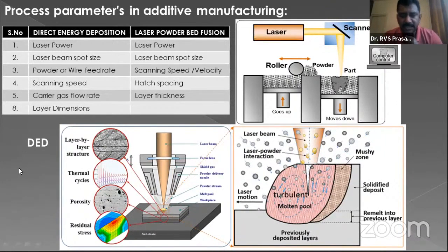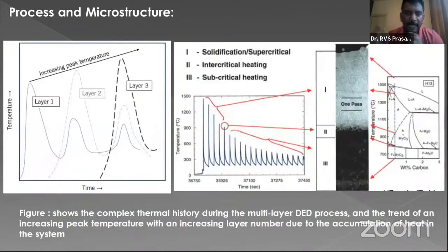However, in the current scenario, by applying these new technologies, one can easily repair, because you have a 3D drawing of the actual component and you know which locations have issues. Those areas you can build up layer by layer and polish or grind, so that you end up with a component which is repaired but looks like a new component. That is one of the critical advantages of direct energy deposition.